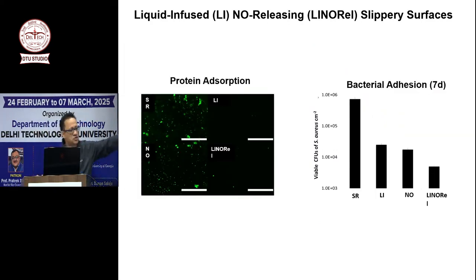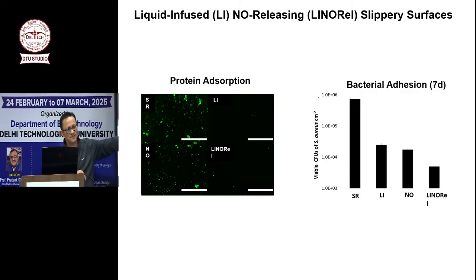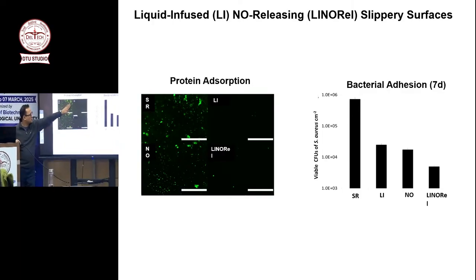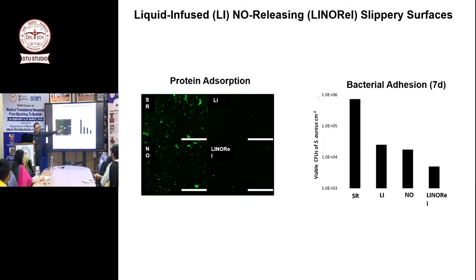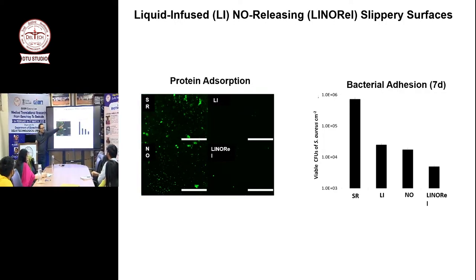This figure got a little bit messed up. This is a control silicone rubber. SR is silicone rubber. NO is nitric oxide releasing surface. LI is liquid infused surface. LINORel is liquid infused nitric oxide releasing surface. And all this fluorescently labeled protein is fibrinogen. On the silicone rubber, a lot of protein is sticking. On the NO surface, protein is sticking. On the liquid infused surface, protein is not sticking, and on the LINORel surface, protein is not sticking. So we made an anti-fouling NO releasing surface.